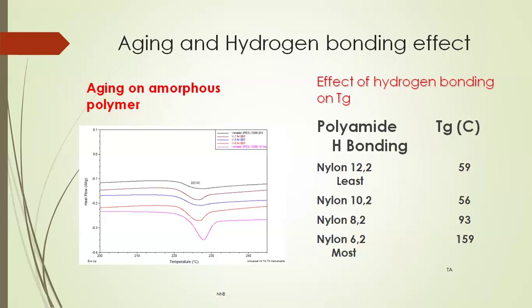And amorphous material is in a highly constrained, high energy state. Any material always tries to go to a lower energy state and wants to settle and stabilize over there. So how to find an aged amorphous sample? Do a DSC. See, this is a totally amorphous sample when you received it from the manufacturer, and with time it ages. How to find out aging? After TG, the glass transition temperature, you get a melting, which is the indication of aging. And as you increase the shelf time, the melting temperature after TG increases. This shows you this is the most aged sample and this is the fresh amorphous sample.